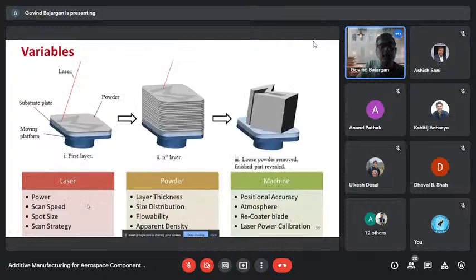So there are parameters which are laser dependent, powder dependent, and machine dependent. Among the important ones, laser power and scan speed are really two of the very important parameters, and then there is spot size. Scanning strategies are also equally important. For powder characteristics, generally we go for flowability and apparent density checks and particle size distribution. And the machine has its own parameters like positional accuracy, atmosphere, recoater blade, and laser power calibrations. These are a few important things for the machine.